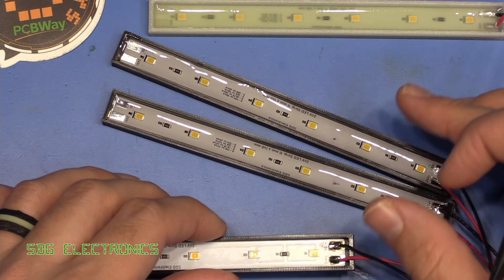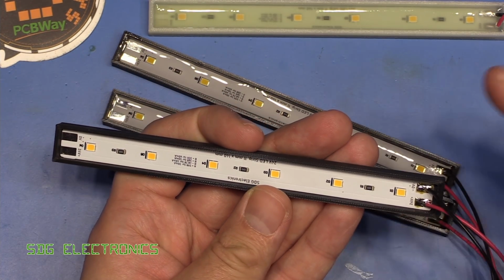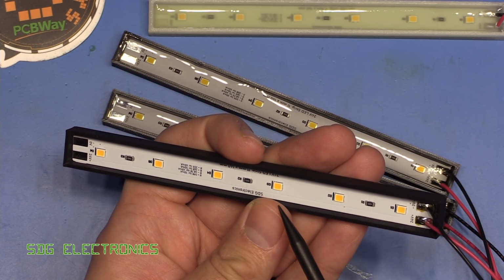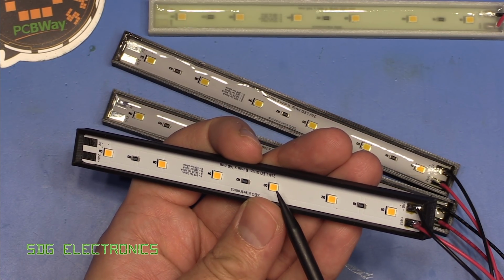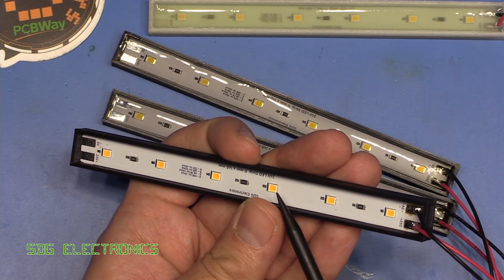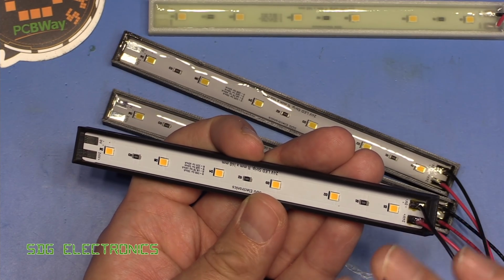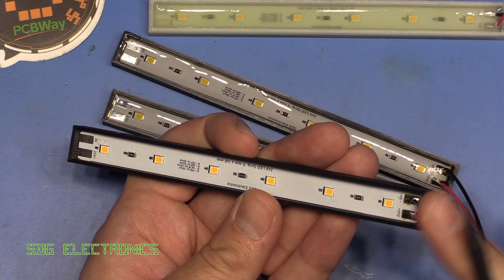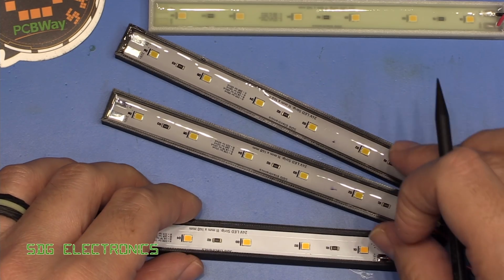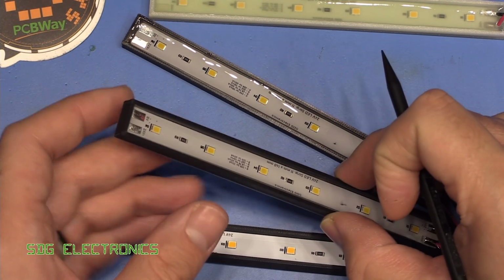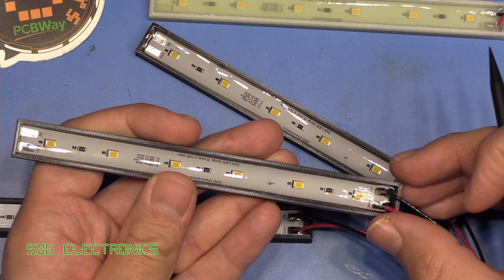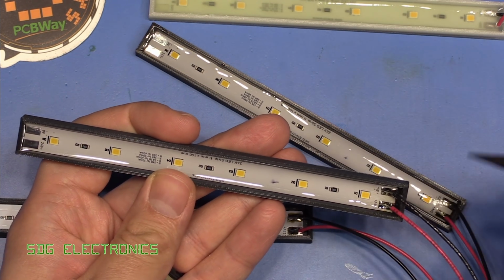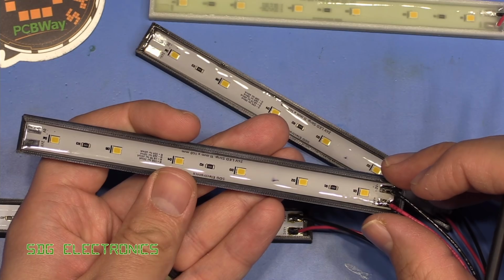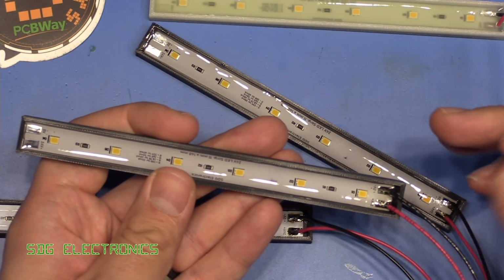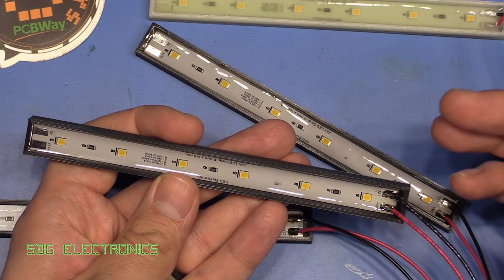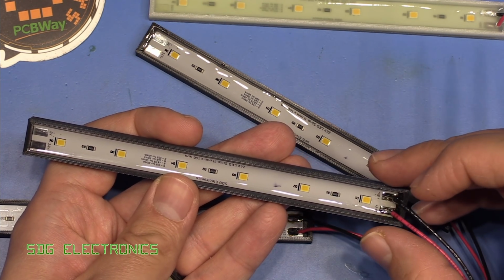But one thing that is quite obvious by eye, these are warm white LEDs. And if you take a look at the color of the phosphor, we've got that very traditional deep orangey colour for the phosphor, because there's a lot more of the phosphor in there that fluoresces towards the red end of the spectrum. However, if you take a look at these ones, they're exactly the same LEDs but are encased in resin. These look really pale, and that's what you'd normally get with the cooler colour temperatures. So it does look like somehow the resin is interacting with the phosphor on these LEDs.